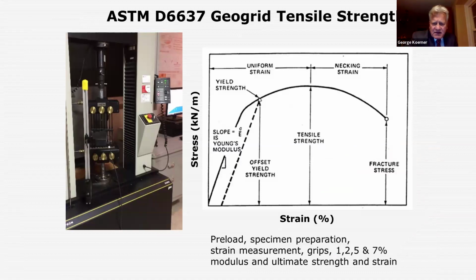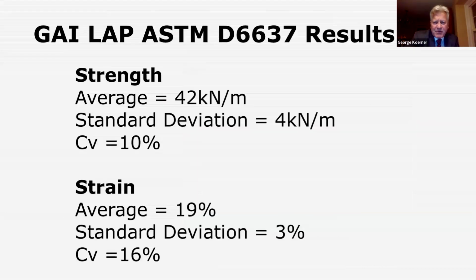That test method, 6637, you're looking at stress versus strain. You're very interested in the preload, the specimen preparation, the strain measurement, the grips, the strain at 1, 2, 5, 7% modulus, and the ultimate tensile strength and strain of the material. So this is what you're looking for in that material. And how do we look for the GAI-LAP program?